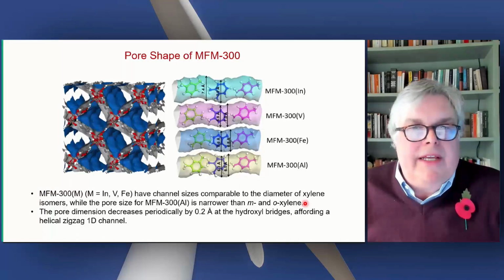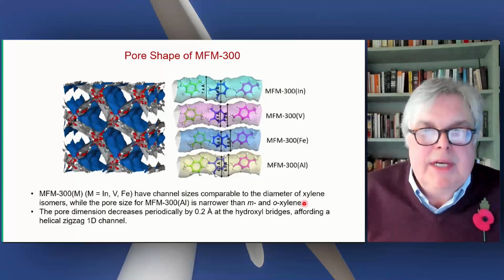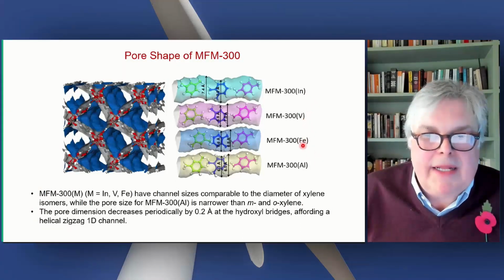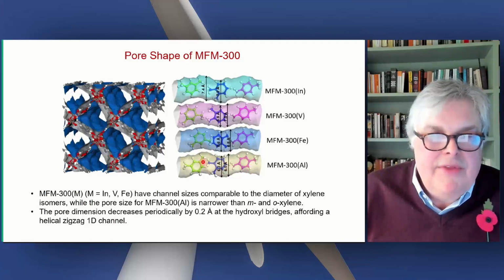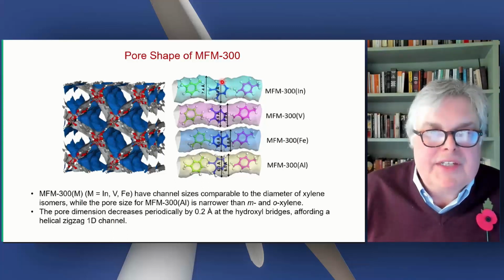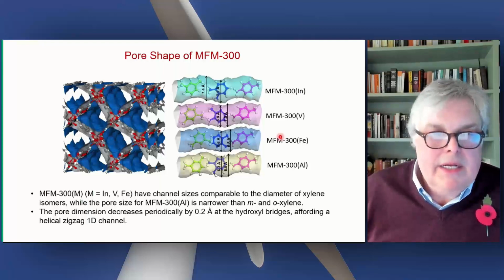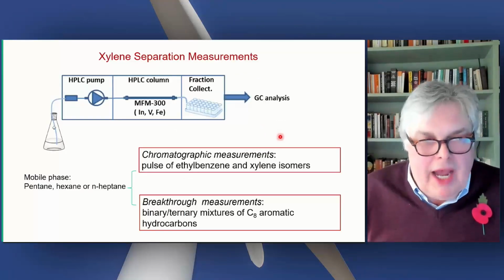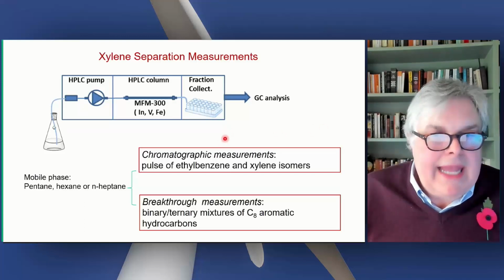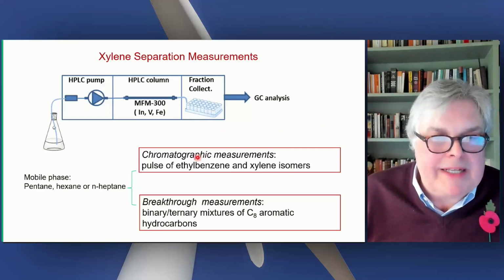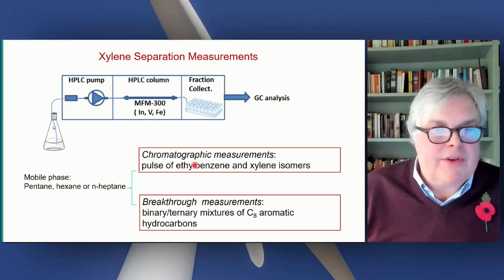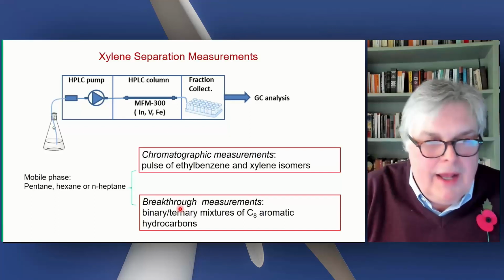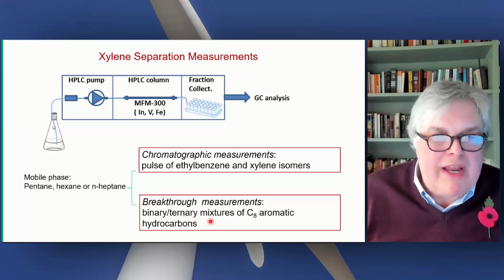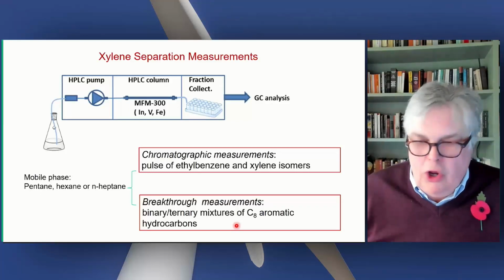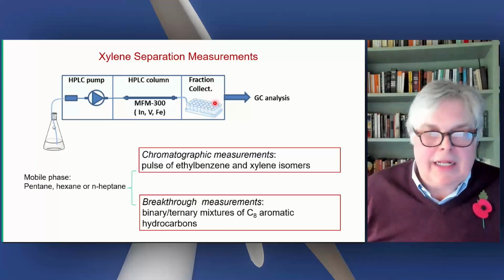If you look at the shape of these MFM 300 systems, they vary quite subtly as you change the metal center, and this just illustrates the tightness with which xylenes pack inside this. The diameter of this pore fits xylene really very, very nicely. And in general, the tighter the pore, the more stable the system. Again, you can either do this via chromatographic measurements, where you pulse the substrate through the column, or you put a breakthrough system in which you have either 2 or 3 C8 components flowing through the column, and you collect the fractions and then analyze them.